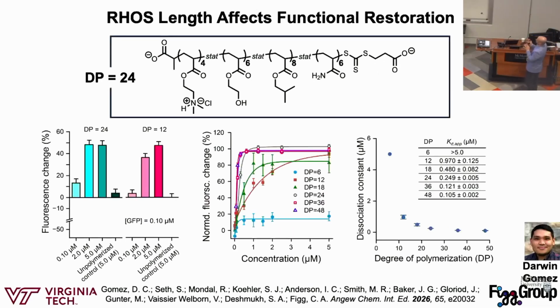So this is just looking at length, and I think this slide has one of the most important pieces of data on it, where if you look at just the monomer control at a pretty high concentration relative to GFP, just the monomers alone don't do anything to the fluorescence. So they're not changing the fluorescence of GFP if you just mix them. They have to be polymerized, which as a polymer chemist is amazing, because you do need polymers to actually get this fluorescence increase.